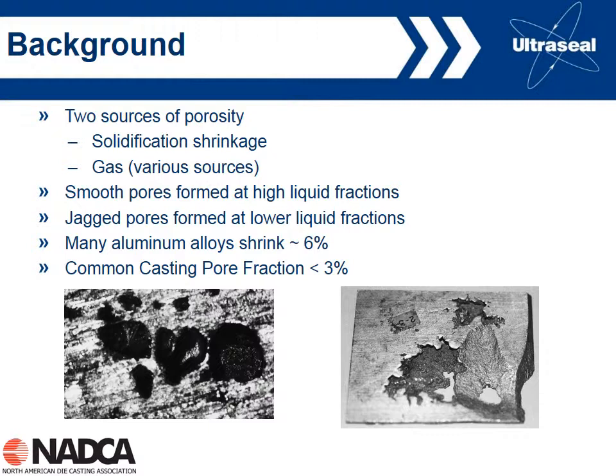It's around a 6% volumetric contraction upon solidification. With zinc, it's a little bit less, 3.5 to 4% or so. And then magnesium somewhere in the middle, probably about 4.5% or so. But if you go and look at the literature, when people talk about the level of porosity in die castings, it's very rare to see a casting that's got more than 3% porosity. So this implies that we can't discount one source of porosity over the other. We're going to get both air entrapment and shrinkage porosity in the die castings.